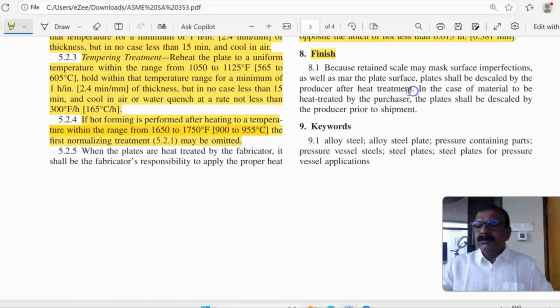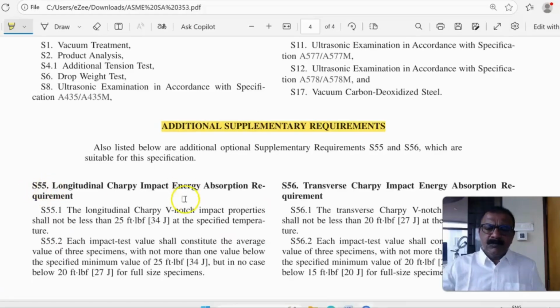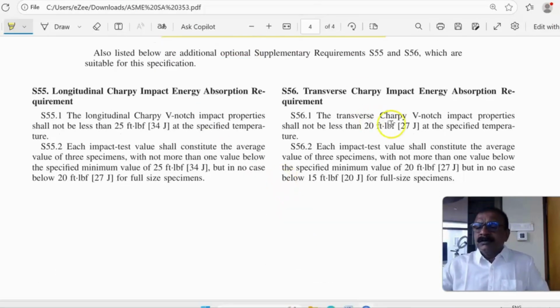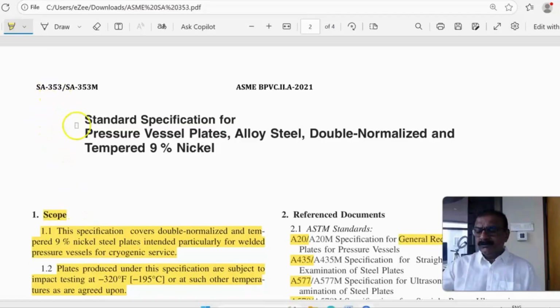After heat treatment, usually scales will form which will mask the imperfections during visual inspection. So these scales should be cleaned after heat treatment. Supplementary requirement S55 is for longitudinal V-notch impact test, and S56 for transverse. We usually use transverse. The minimum average value should be 27 joules, and no value should fall below 20 joules. Whereas in longitudinal, the average is 34 joules and all specimens in the set should be more than 27 joules. I hope you have understood SA 353 through this video.